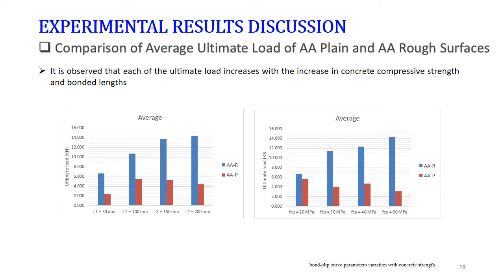Here is the comparison of the ultimate load for the plain surface of the aluminum and the surface that has been roughened, and you can see how much difference it made when we have the surface of the aluminum treated, the blue ones here, where R is for roughening the surface. The average ultimate load changes drastically. You can see here.